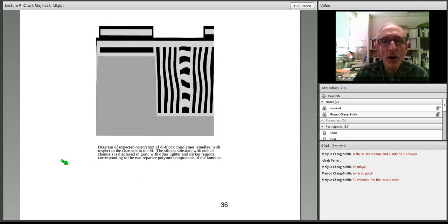Okay, now suppose somebody was interested in studying a diblock copolymer system. Diblock copolymers are hydrogenous objects, of course, and we can hydrogenate one part and deuterate another. Let's say I have polystyrene and polymethyl methacrylate diblock copolymer system. Make the polystyrene deuterated and the polymethyl methacrylate hydrogenated. We get a huge phase contrast.